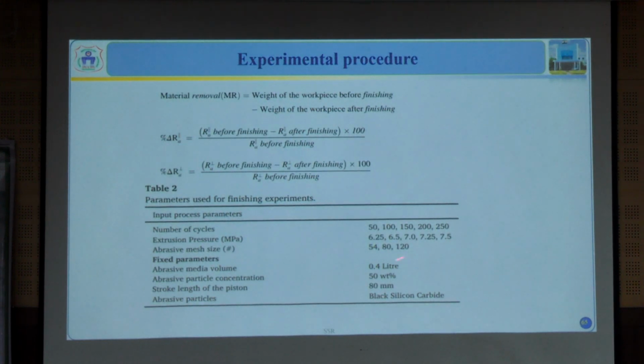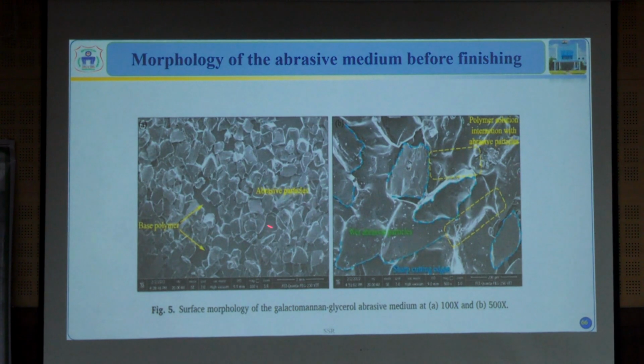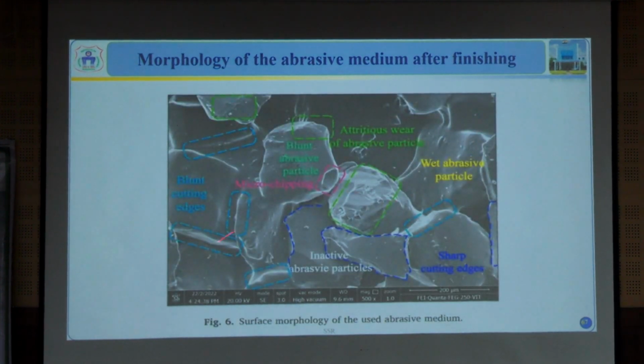These are some of the input parameters which I discussed, and these are some of the calculations of how the material removal is calculated, and the abrasive finishing rate in percentage. And this is a SEM morphology of the media prepared in the case study, where we observe the abrasive particles and the base polymer, the galactomannan polymer, and the abrasive sharp edges. In the used media, after finishing, you can see the wear on the abrasive particle, and also some micro chipping and blunt cutting edges.